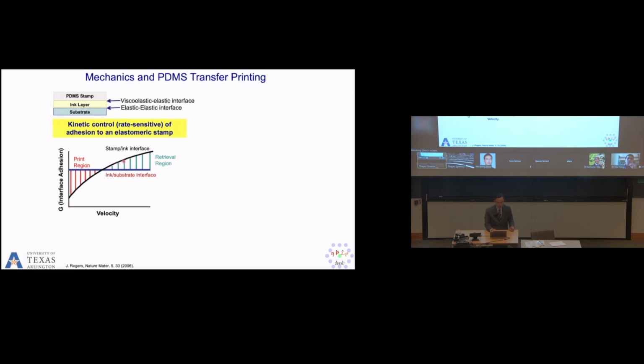The key here is that by controlling the speed, the adhesion between the PDMS stamp and your elastic solid will change. Say you have a bottom solid, a solid film, and a flexible PDMS stamp. If you pick up very fast, you get very strong adhesion between your PDMS stamp and your solid, so you can peel off your solid membrane. When you need to print, you peel up very slowly. Then the adhesion force between your thin film and your substrate is larger than the adhesion force between your PDMS stamp and the film you want to release.